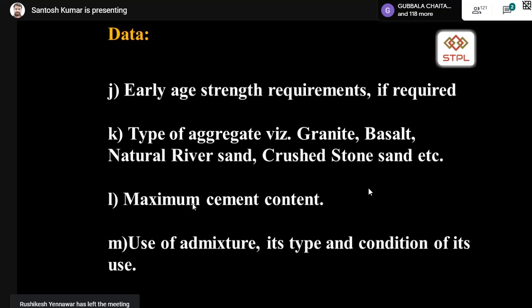So early age strength requirements I already discussed, and type of aggregate. Before using a particular aggregate in your concrete, better get a petrographic examination done. It classifies which type of rock you are using, whether you are using granite, basalt or limestone or sandstone, whatever it may be. And type of aggregates deals with, when it comes to fine aggregates, whether it is river sand or crushed sand. One thing I want to focus on here is, people still have a miscommunication about crushed stone sand being used in concrete, but when it comes to high performance, high strength concrete, crushed sand is more preferable than natural river sand.